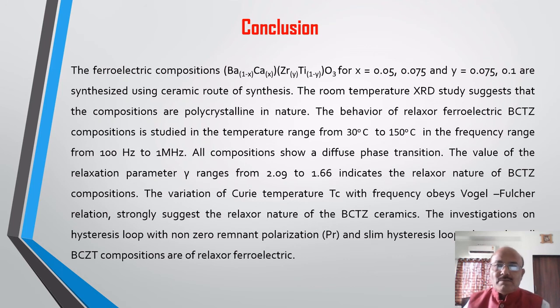Now the conclusion of my paper. The ferroelectric BCZT materials are synthesized using the ceramic route of synthesis. The room temperature XRD suggested that the compositions are polycrystalline in nature. The behavior of relaxor ferroelectric BCZT compositions is studied in the temperature range from 30 degrees to 150 degrees centigrade in the frequency range from 100 Hz to 1 MHz.